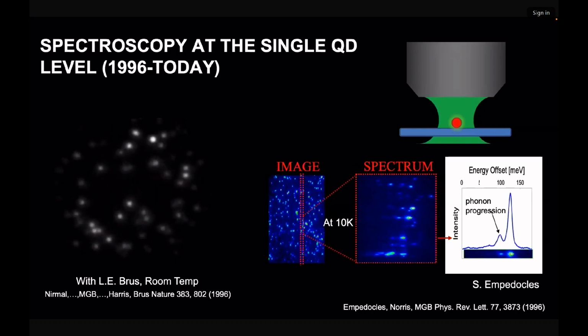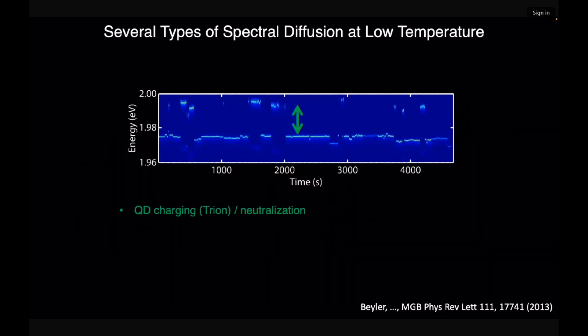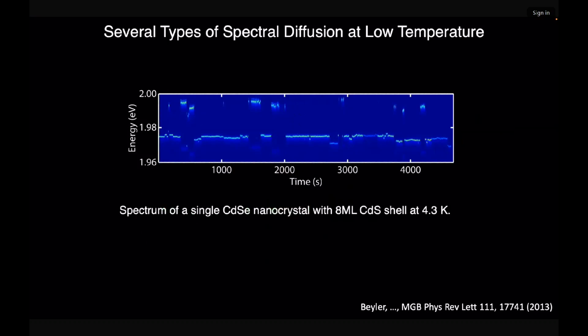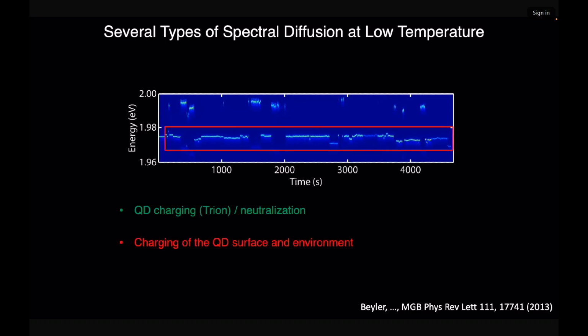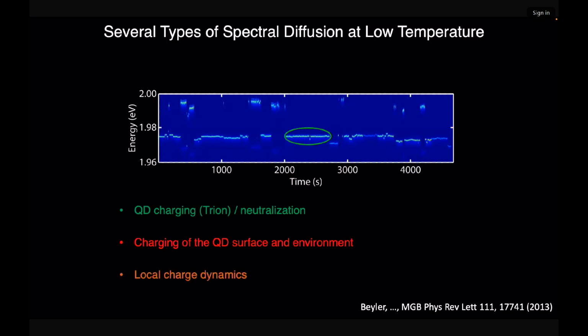We can go time on this axis here, energy on this axis. Look at the light coming out. We see these spectral jumps, which we can then identify as charging of the dots, or charging of the surface and then motion of the electrons on the surface, or when you have very small shifts in the energy here, maybe local charge dynamics or dipole moments that are going like this, changing the Stark effect. So you learned a lot of really subtle but really interesting physics along the way.